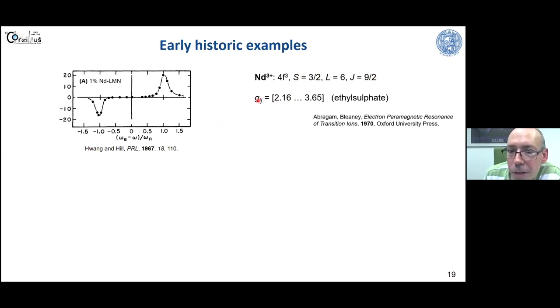And here you can see the g factor or the g matrix practically can take values between 2.16 and 3.65 dependent on the orientation. And you see immediately that the free electron g factor 2.0023 is not even within the range of this g tensor. So there's no way with an EPR magnet at high field that you can actually hit any resonance without completely sweeping this magnet with a completely off field.